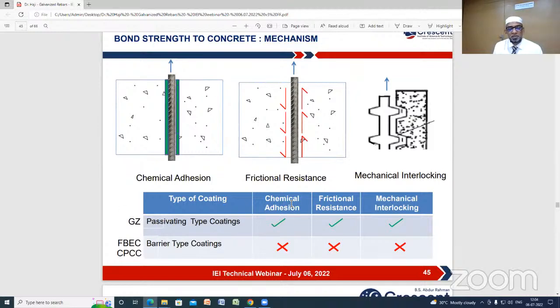In galvanized rebars, all these things are available in a good manner. The adherence of the concrete to the galvanized rebar is very good. Frictional resistance, yes. Mechanical interlocking, since it is similar to the conventional rebar, no issues. There is no closing of the annular space between one rib and another because of the coating. In the case of barrier type coatings like fusion bonded and CPCC, there is a possibility that these three mechanisms which contribute to the bond strength may get disturbed.